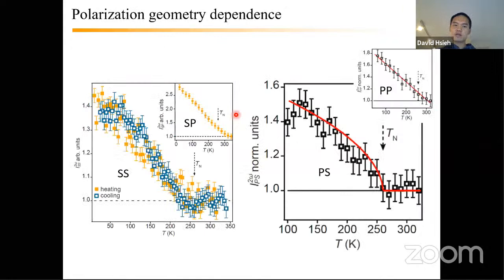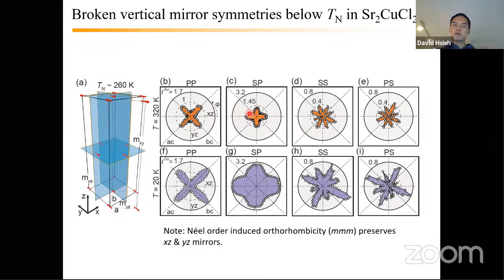We align our crystals in such a way so that this is on cleaved SCOC, but the alignment is such that at high temperatures it looks very consistent with what it should look like, and so that makes us trust the low temperature results, because there are ways in the lab we can make sure of that. Upon cooling, you do have some contraction, but our contraction doesn't lead to tilt. It just leads to motion along the z-axis of our cryostat, along the rotation axis of the scattering plane.